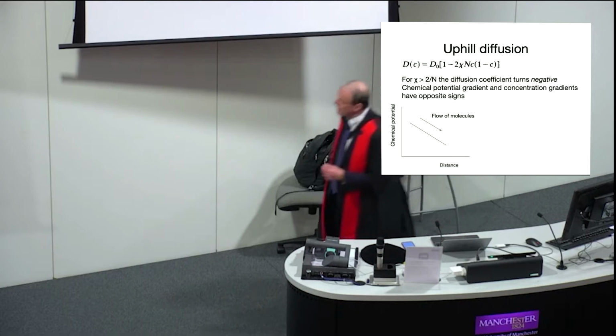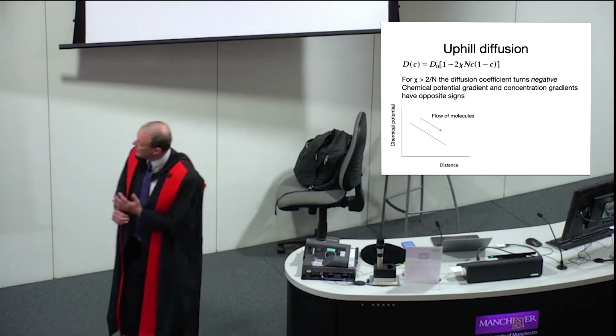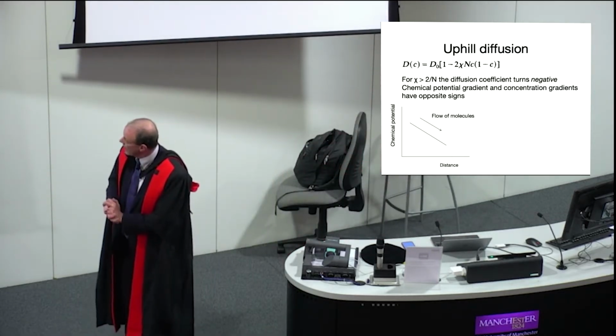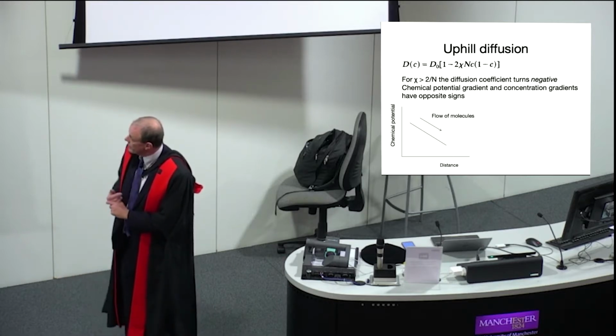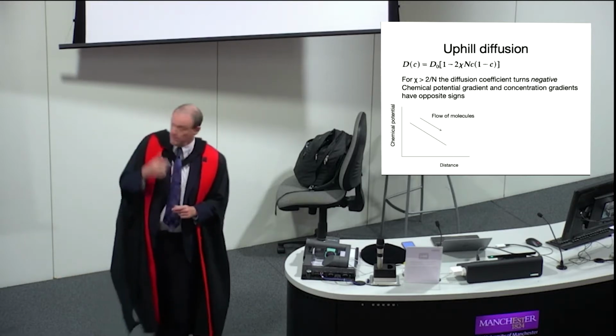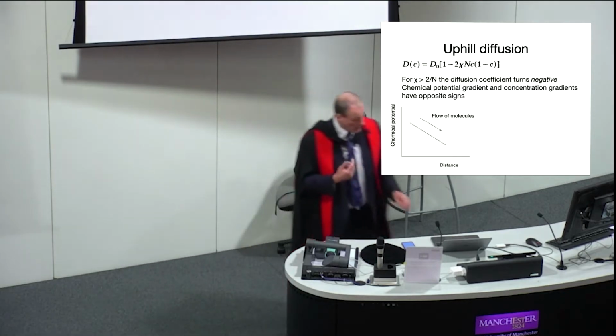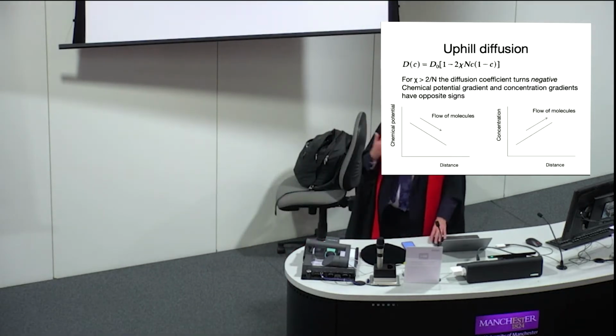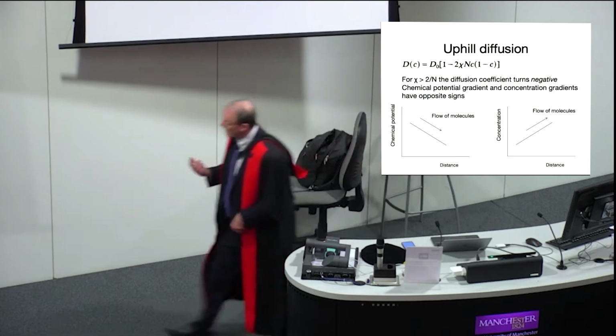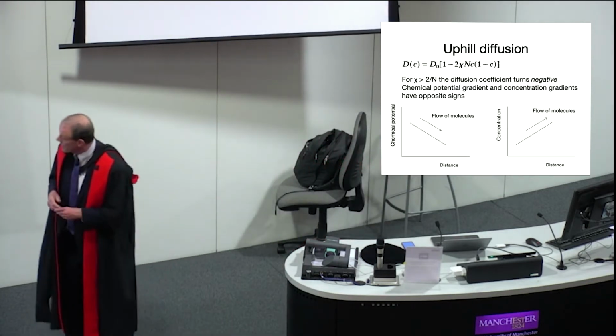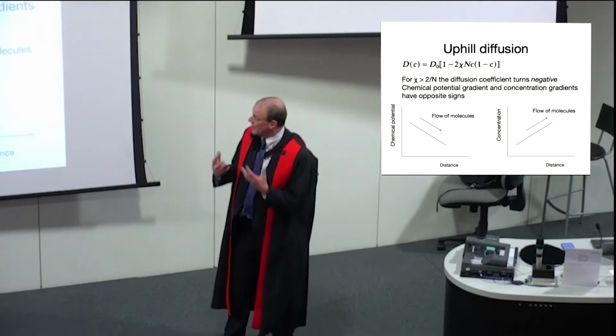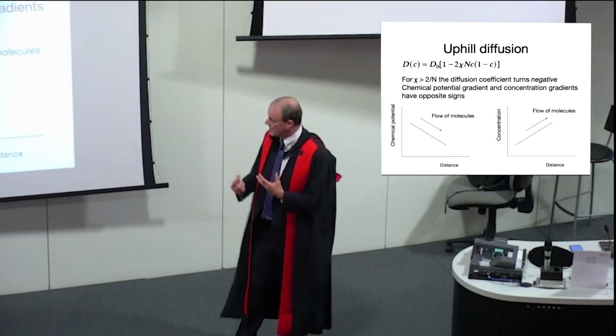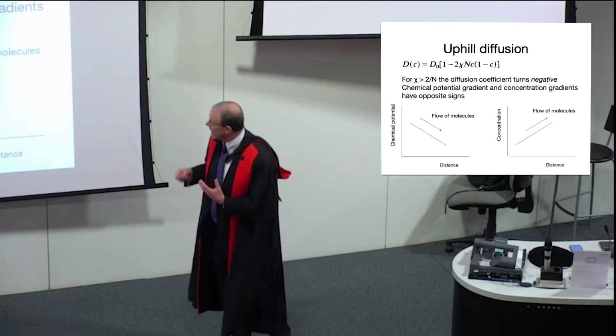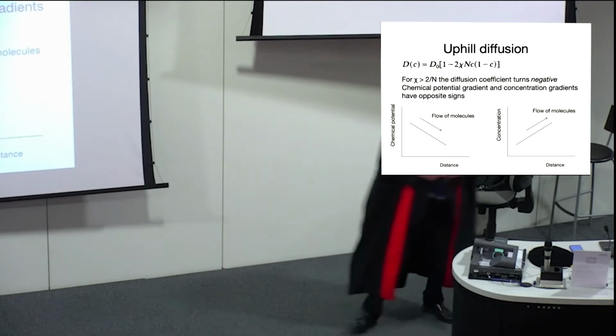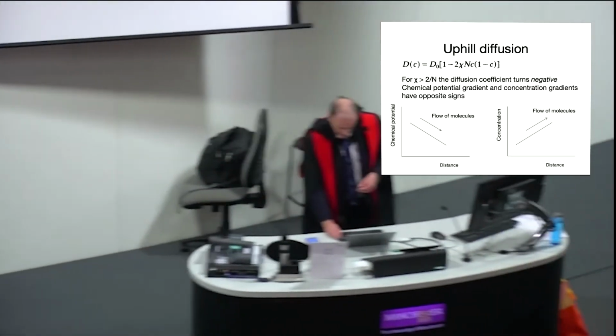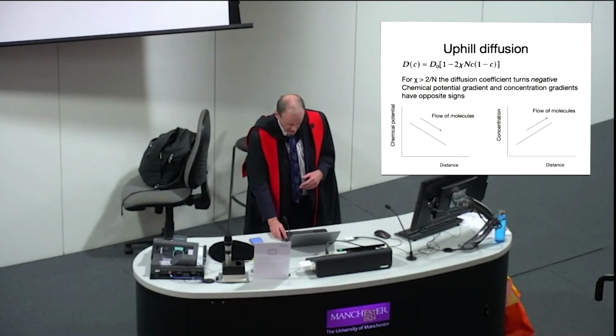But what's interesting about this equation is that if chi is greater than 2 over n, the diffusion coefficient turns negative. And this means that the flow of molecules, the concentration gradient, is in the opposite direction to the chemical potential gradient. And so, whereas, just as I've always said, molecules want to flow from high chemical potential to low chemical potential, in this case, that corresponds to molecules flowing the wrong way, from low concentration to high concentration. You get this negative diffusion coefficient.